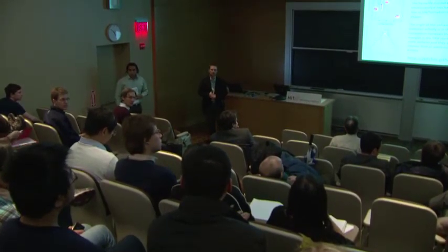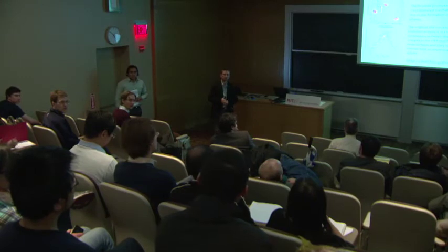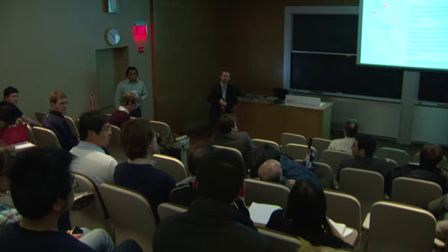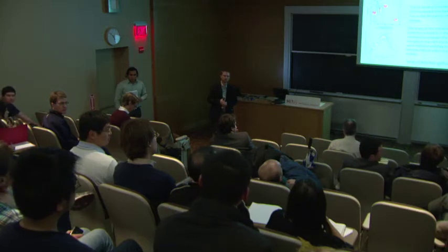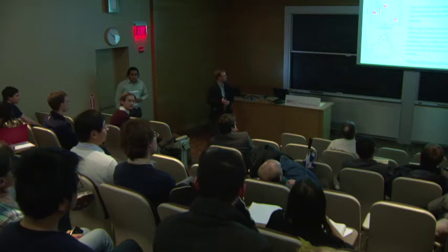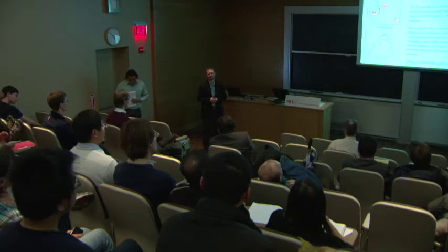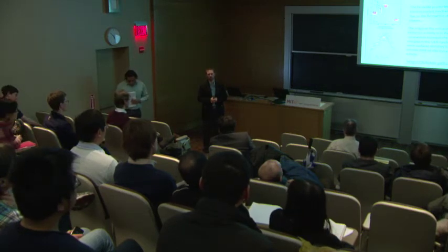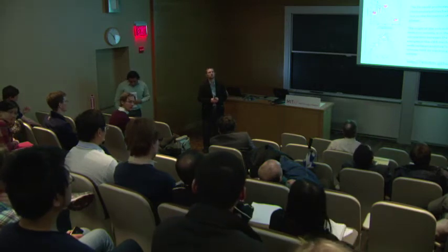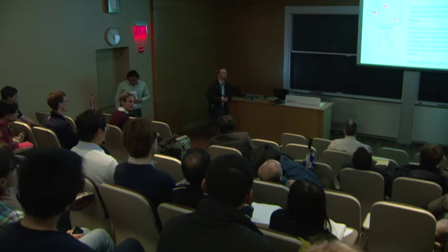So the electrolyte you mentioned in this talk is the hydroxide species of the cation. Right. Have you looked at the effect of just the cations with a non-coordinating anion, such as tetrafluoroborate, hexafluorophosphate? Yeah, so we need the high pH to stabilize nickel oxide. Right. So if you did it at neutral conditions, it would just corrode. No, I mean you would add sodium hydroxide at the same time with the other two. Yeah, I see. No, we haven't tried that.